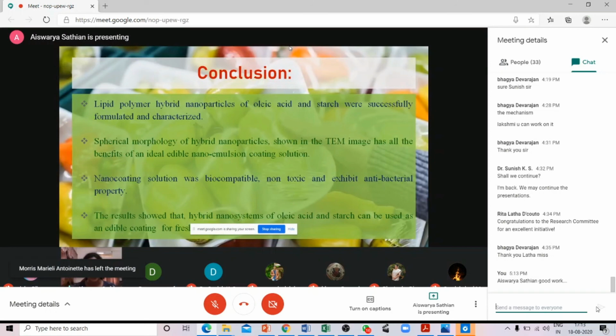The TEM image showed a quasi-spherical structure without any damage in the outer covering, and it has the right encapsulation also. And this nano solution does have novelty because most of the research is happening in polysaccharide nano coating. There is not much research going on in this hybrid system nano coating.